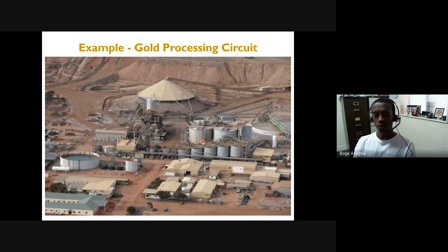So they do not actually do a lot of complicated beneficiation. They do use gravity separator. But other than that, once they produce the concentrate, they do direct leaching. They actually also leach the tails as well. Because they know they have some gold in the tail, they also leach the tail and the concentrate. And it's a relatively simple process.